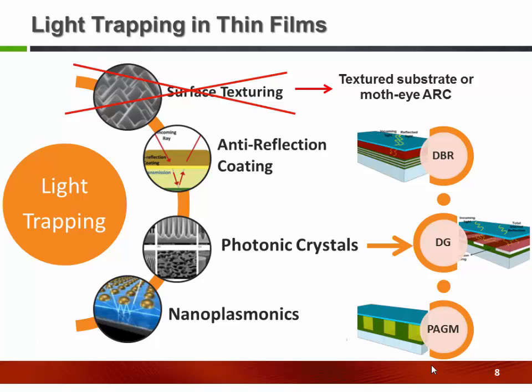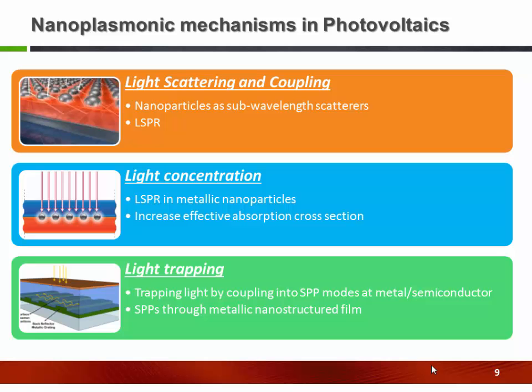But one new field of research is nano-plasmonics, for which I'm going to give an explanation and some simulation results. Nano-plasmonics mainly causes an enhancement in absorption through three different mechanisms. Sometimes we use just one of these mechanisms, but sometimes we can incorporate all of them for enhancement of light trapping in the device. The first one is light scattering and coupling. We could create particles that scatter light, and initiate forward scattering in order to enhance the path of light inside of the absorber layer in order to increase